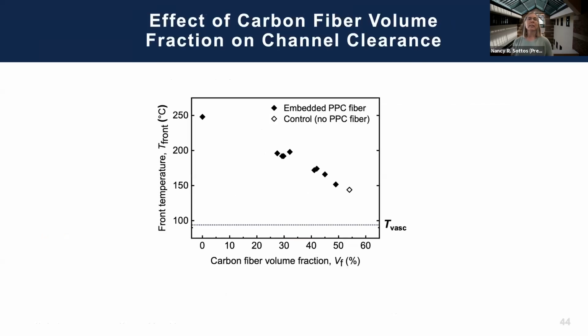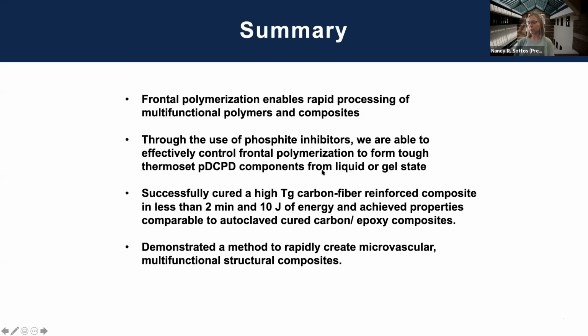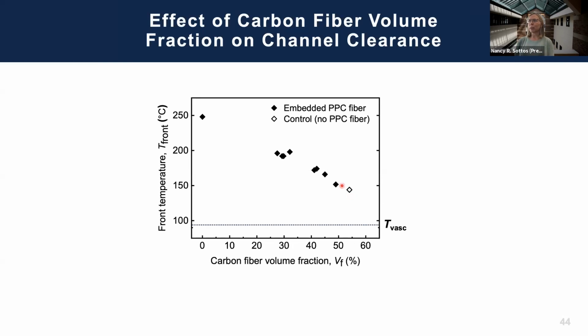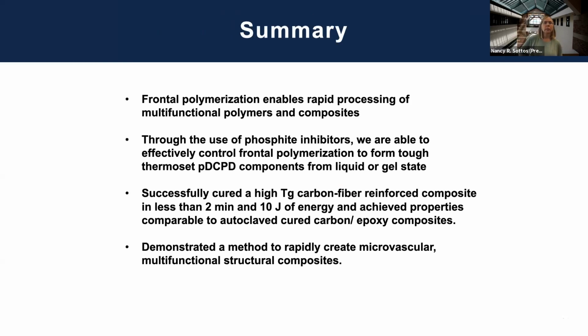So that's a good result. And we've been working on this issue of the effect of the carbon volume fraction. Again, Philippe's group has been doing the modeling, and through this compaction process and keeping insulating plates, we've made it all the way to 50% volume fraction, and we're pushing forward. There's work in progress right now to push on and get these higher volume fractions and also go to more complex networks.